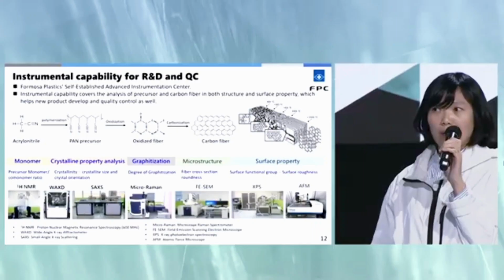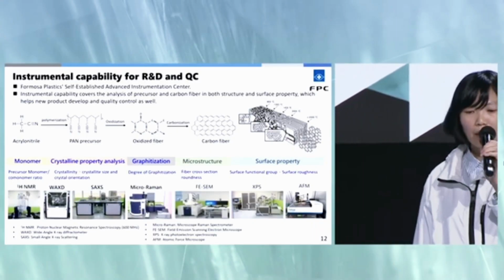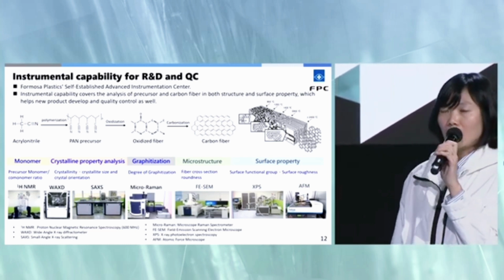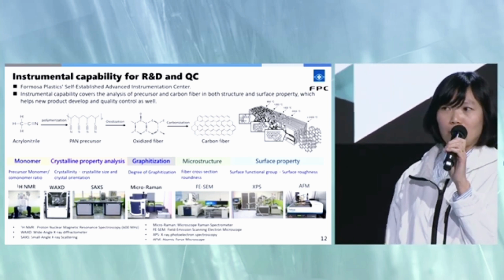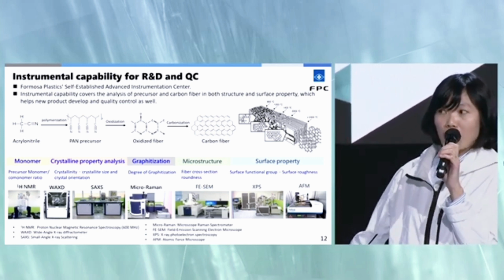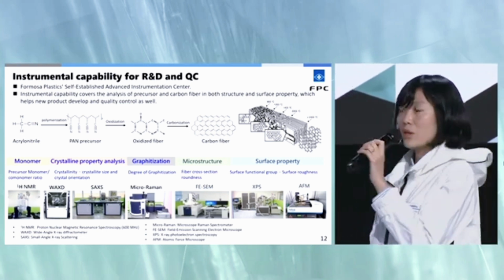Not only the precursor process development, we also established an instrumentation center to help the development. For the monomer ratio, we established proton NMR to check the ratio and the polymerization, so the monomer weights will be accurate for our demands. And also to understand the crystalline property, because it's a crucial factor for the strength, we established wide-angle X-ray diffraction and small-angle X-ray scattering.